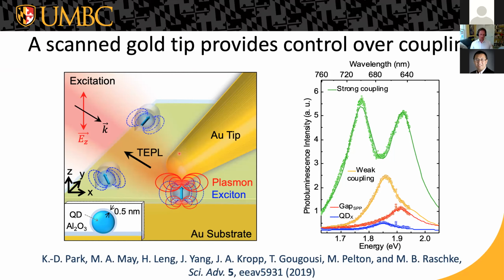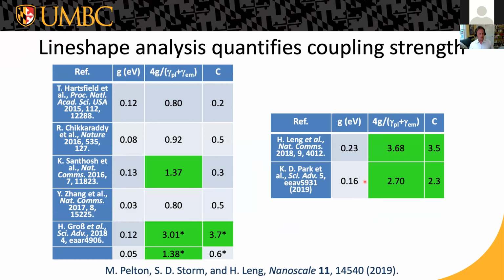And I should say we do that coupling strength calculation both for the experimental data and for these theory calculations by fitting the line shapes that we have to our coupled oscillator model. So we're not just looking at how far apart the peaks are, because that can be misleading, especially in this induced transparency regime, but by doing a line shape analysis. And so for our two cases, the first one of our nanoparticle above the surface and then our scanning probe tip above the surface, we are solidly into the strong coupling regime and into this high cooperativity regime, which enables the quantum information applications.